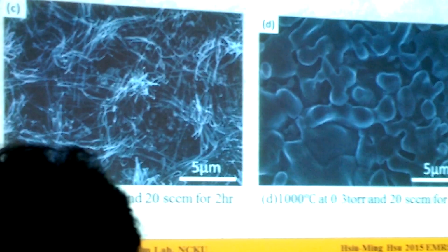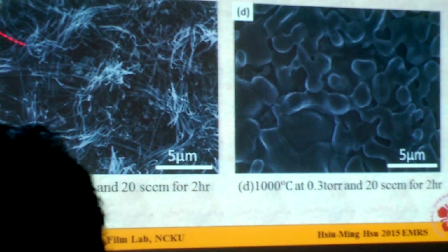It was difficult for us to call them wires. When we raised the temperature to 850 degrees Celsius, the result is figure 2C: products with the highest aspect ratio, with diameters about 20 to 40 nanometers. Now we can call them wires.